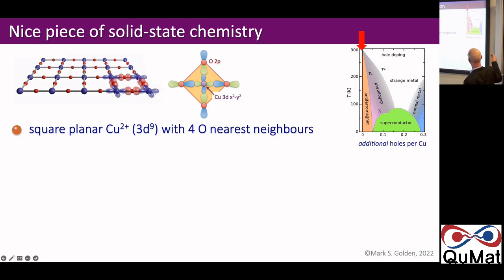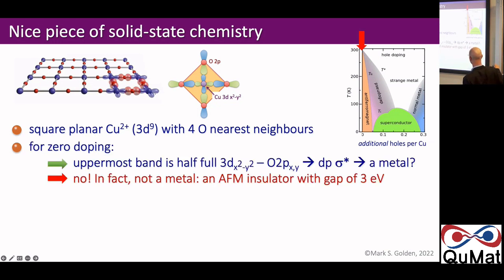For those, which we call the parent compounds, they're antiferromagnetic insulators. And they're antiferromagnetic insulators because of the strong Coulomb repulsion between two charges in this copper 3d x squared minus y squared. So if you have d9, let's forget the eight underneath, right? They're all filled, so they're not interesting for the physics of the compound. We have one band, which is half filled, and density functional theory will tell you it's a metal. You make it, you do experiments on it, you see it's an antiferromagnetic insulator with a gap of about 3 electron volts. So this is immediately a signal to everyone in the field that these superconductors may be quite interesting because they're not born from regular Fermi liquid metals, but born from doped Mott insulators.